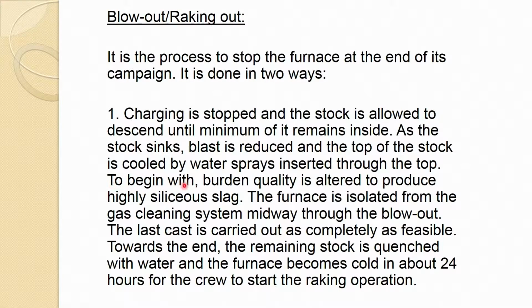line. So, to begin with, burden quality is altered to produce highly siliceous slag. Which means you put silica gravel or quartz in that. The furnace is isolated from the gas cleaning system midway through the blowout. The last cast is carried out as completely as possible. Towards the end, the remaining stock is quenched with water and the furnace becomes cold in about 24 hours for the crew to start the raking operation.